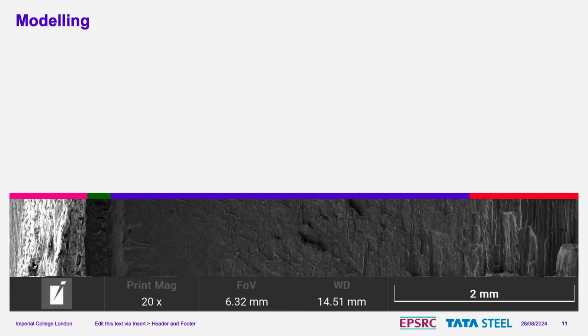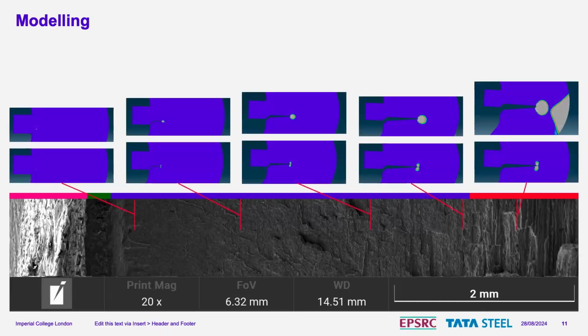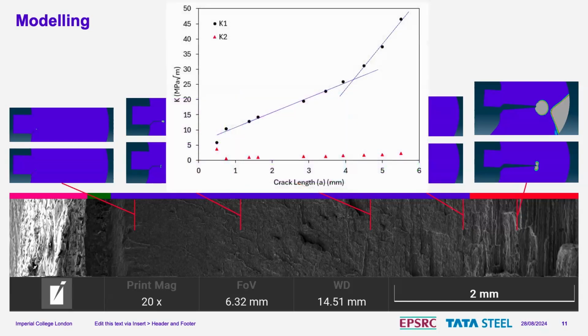And so I did a very simple model, just a 2D simulation. On the top we get our plane stress, and on the bottom we get our plane strain. You can see that they line up with each of these points along the crack surface. And after that ductile tearing starts, we get plastic collapse in the back of the sample. I also did a purely elastic simulation and plotted my K1 and K2 from that for different crack lengths. If we take these lines, you can see that the point at which they cross lines up reasonably well, around 4 millimeters, with the point at which we get ductile failure in the material.